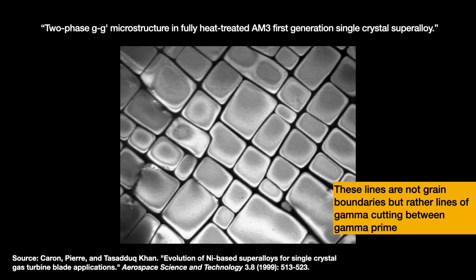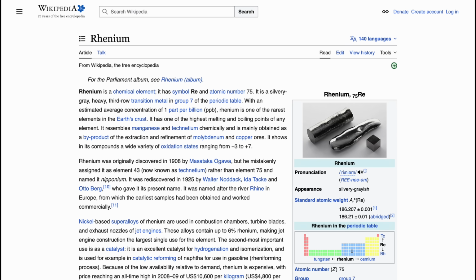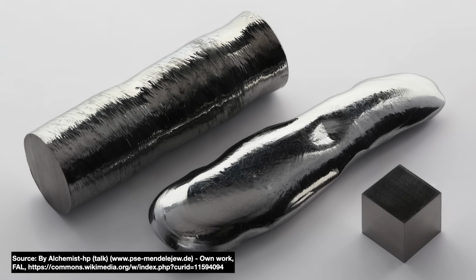People went back to the drawing board and created new superalloy mixes specifically targeted to the method. Most would incorporate a very rare element called rhenium. Unlike the so-called rare earths, rhenium is actually rare, the byproduct of a byproduct. They only produce about 50 tons of it each year. Adding rhenium to nickel-based superalloys in proportions of up to 6% dramatically improves creep resistance and overall temperature resistance for single crystal superalloys. Thus, the majority of the world's rhenium goes into such superalloys.